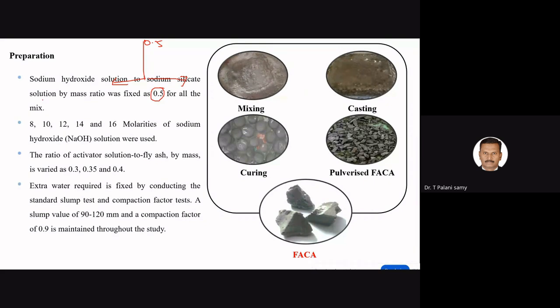activator solution. Another very important factor is the molarity of the sodium hydroxide and sodium silicate solutions. We tried different molarities, from low to higher. For example, 8, 10, 12, 14 and 16 molarity of sodium hydroxide NaOH solution was used for this investigation. The ratio of activator solution to fly ash, this is a different activator solution to fly ash, I can take varying from 0.3, 0.35 and 0.4.